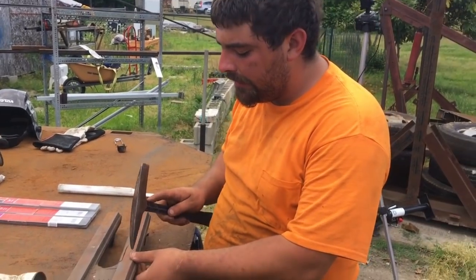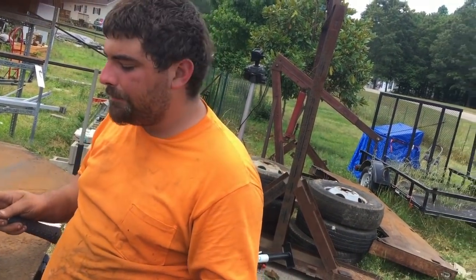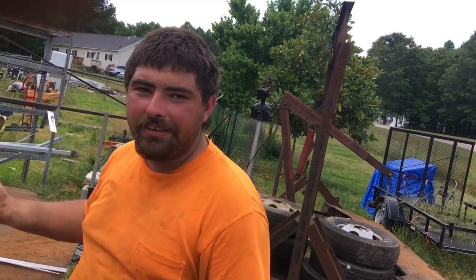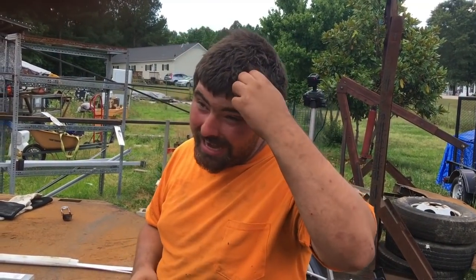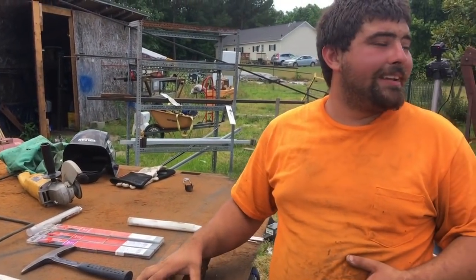And you'll peen it, you'll go around it, and as soon as you're done peening it, then you'll take it and you'll throw it in your sand and leave it overnight. You bury the thing in sand, leave it overnight, come back out, blow it out. You're good to go. Now, if it's a critical component like an engine head, before I stick it in the